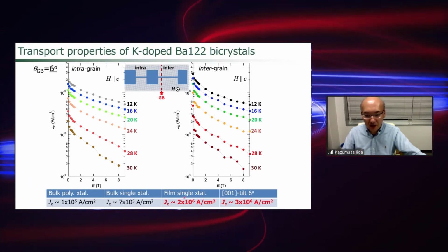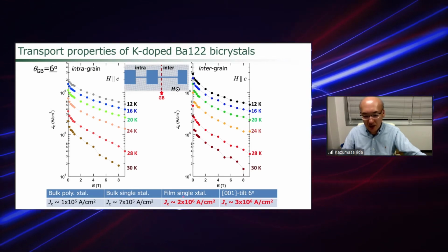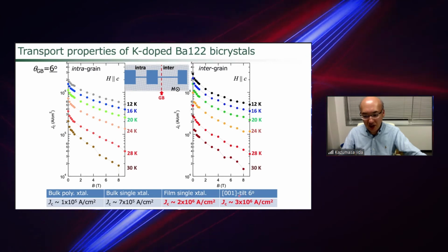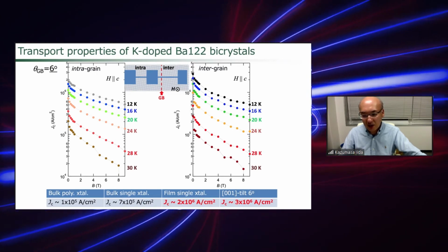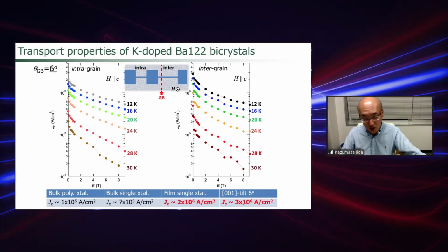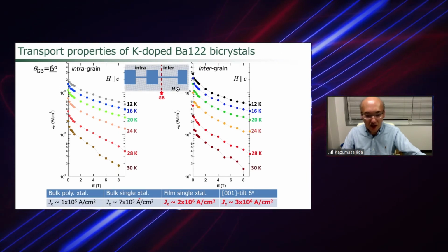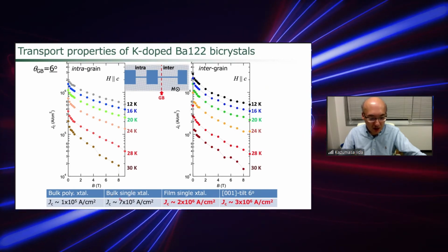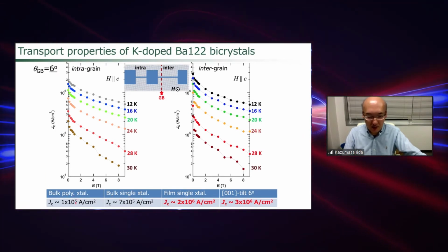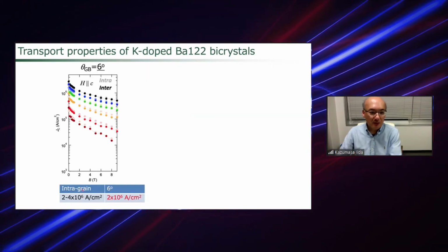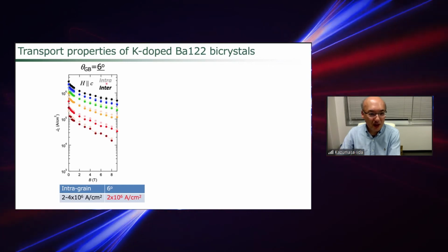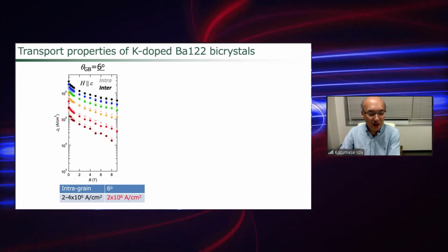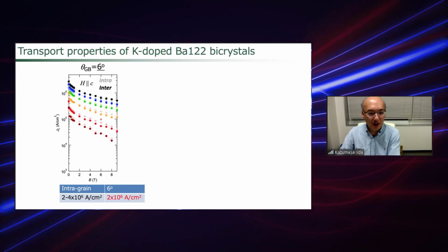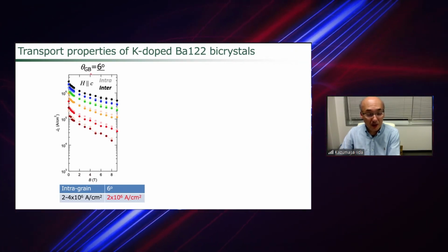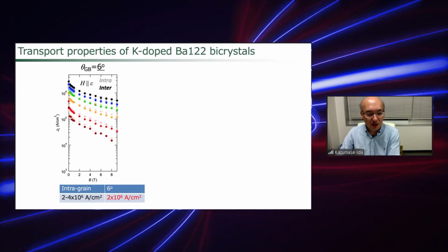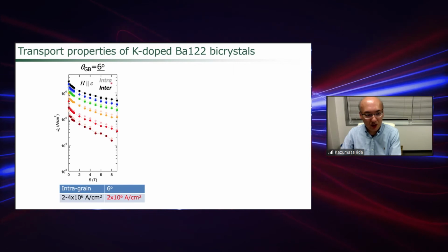And here again, I show you the absolute value of the intragrain Jc and the intergrain Jc. Both are almost on the order of 1 mega ampere per square centimeter, which is one order of magnitude higher than the bulk single crystals as well as the polycrystalline samples. So here is the same plot, but we plot the intragrain and the intergrain Jc together as a function of the applied magnetic field. As I mentioned before, the grain boundary angle of 6 degrees has almost the same Jc for the intra- and the intergrain.